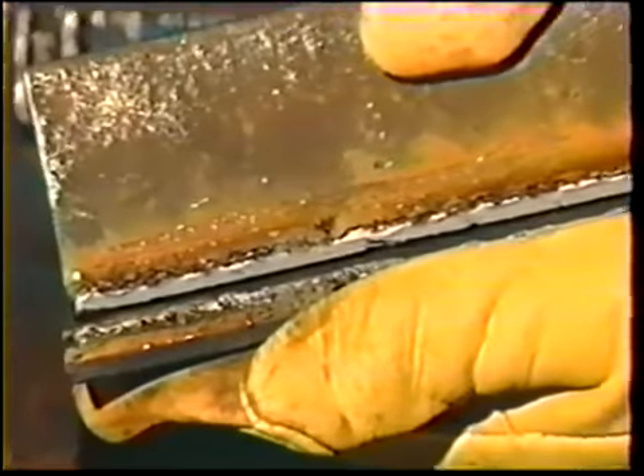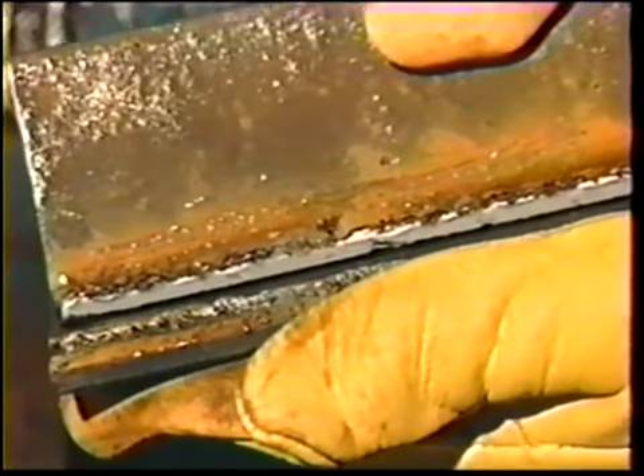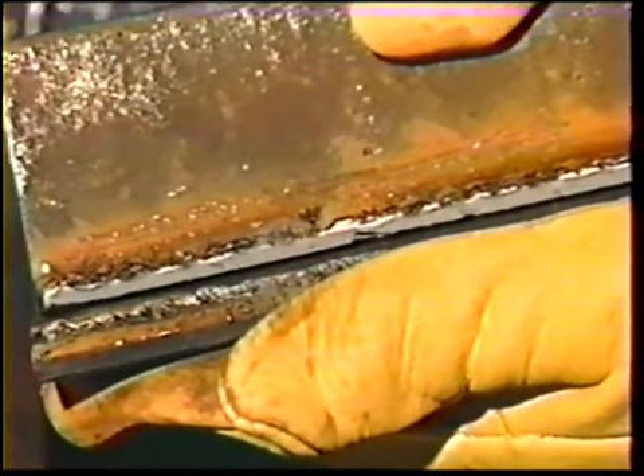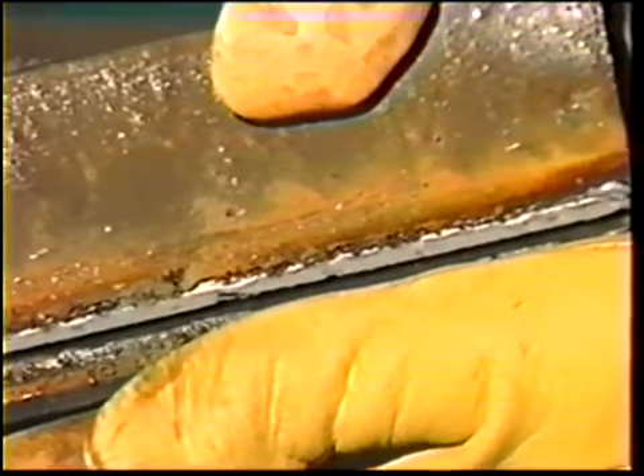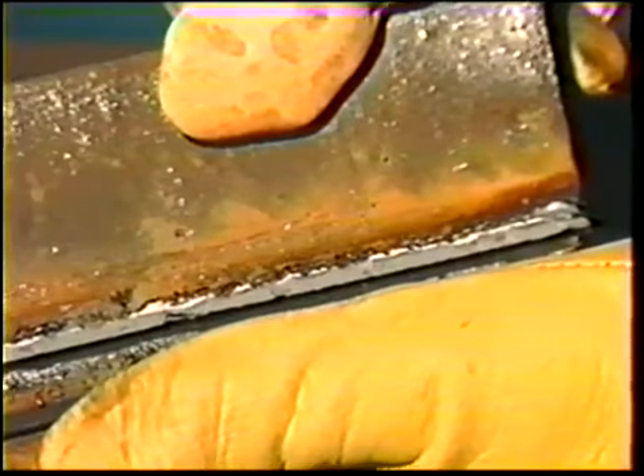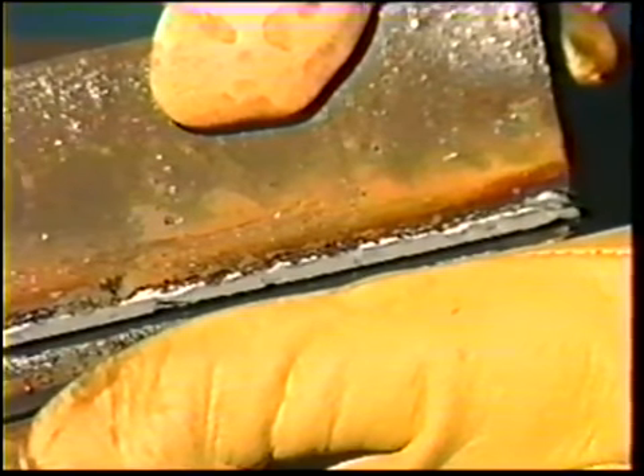The fractured surface of the weld shall show fusion to the root of the joint and shall exhibit no incomplete fusion to the base metal, and there shall be no inclusions or porosity larger than 3/32 inch in greatest dimension.